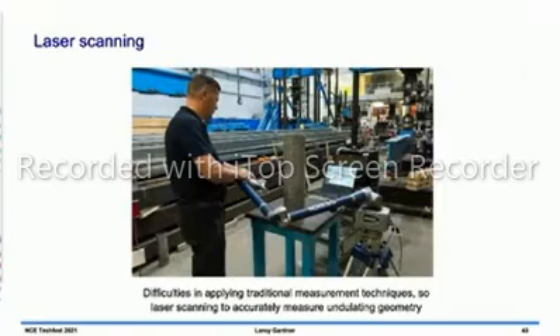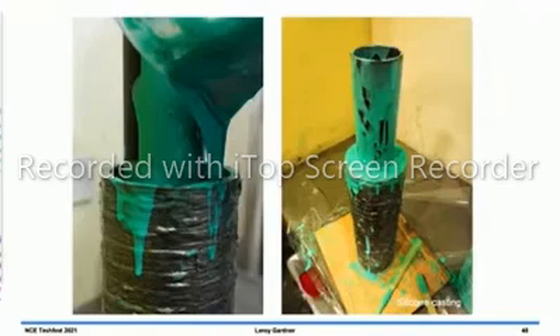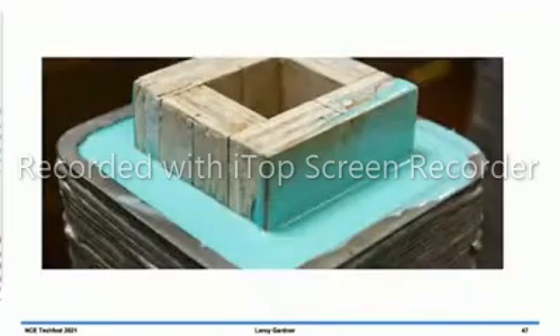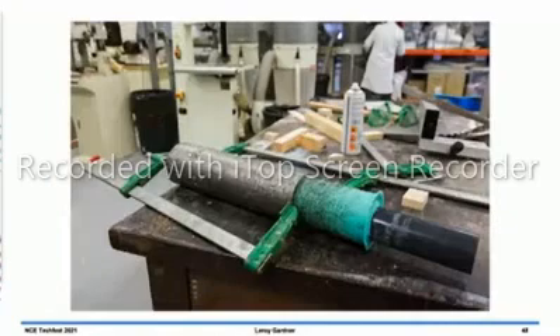Because of the undulating geometry, it wasn't quite so easy to simply measure thicknesses and dimensions and so on. So we used 3D laser scanning in order to capture a full digital image of the sections. They're tubes, and so it's not so easy to scan the inside of tubes. So we decided to do some silicone castings. So we filled up the tubes with silicone, it set. We then pulled out the inserts, which was not quite as easy as we hoped it would be, but they came out eventually in one piece.